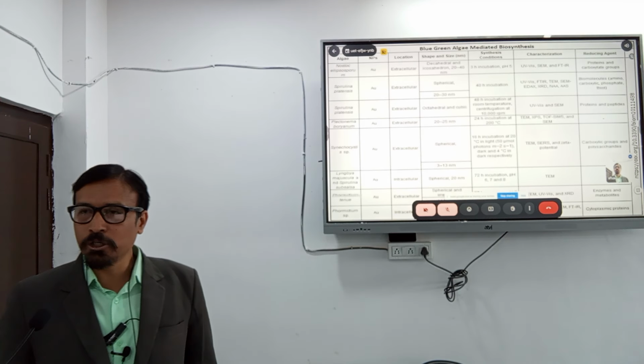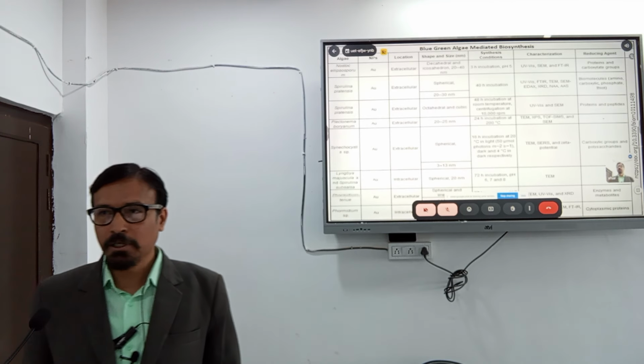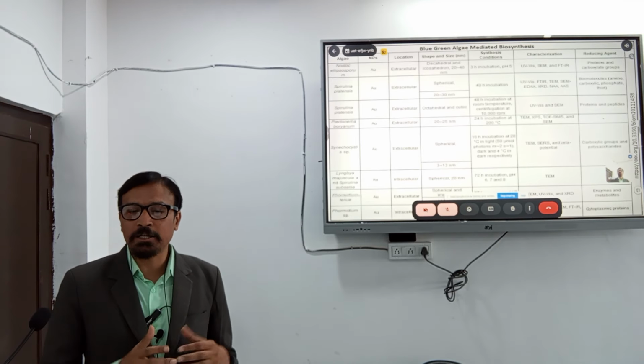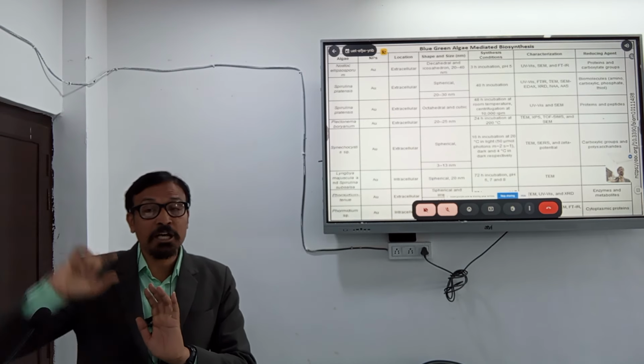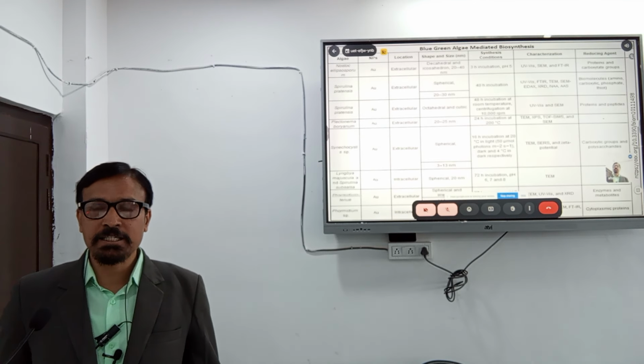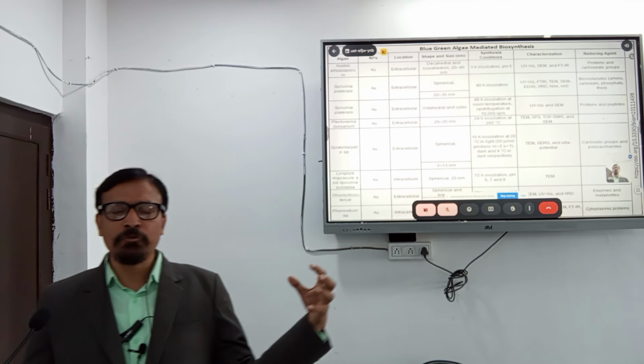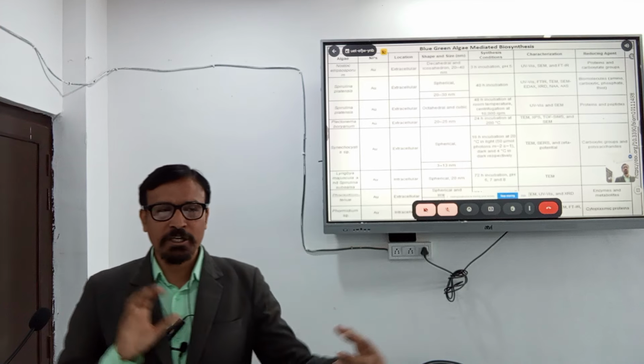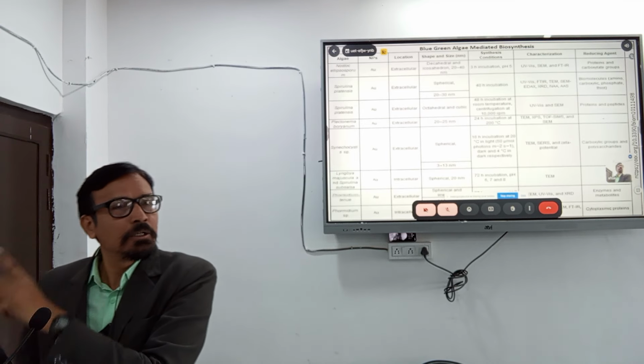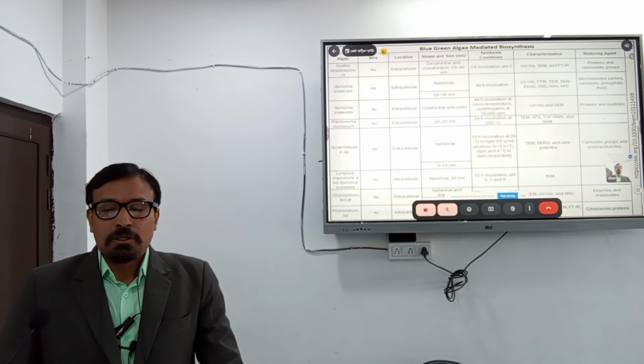Plectonema boryanum is another algae with which we can synthesize gold nanoparticles. The location is extracellular, the size of nanoparticles will be in the range of 20 to 25 nanometers, and the synthesis condition is 24-hour incubation at 200 degrees Celsius. That means a very high temperature is required for this synthesis. The characterization can be done with TEM, XPS, TOF, that is time of flight, TOF mass. So we can connect many equipments also, like GCMS. One task will be done with one equipment, and another task will be transferred to the next equipment. That's why there is a combination of many equipments many times.